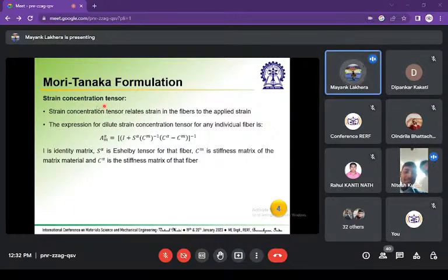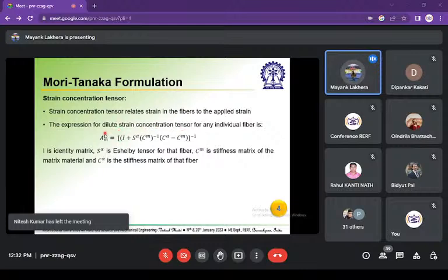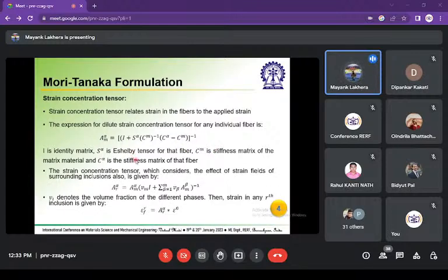So the strain concentration tensor relates the strain in the fiber to the applied strain. If there is a single inclusion in the matrix, then that strain concentration tensor is known as the dilute strain concentration tensor. For any individual fiber, it is given by this expression, where I is the identity matrix, S alpha is the Eshelby tensor, CM is the stiffness matrix of the matrix material, and C alpha is the stiffness matrix of the individual fiber, and again CM is the stiffness matrix of the matrix.